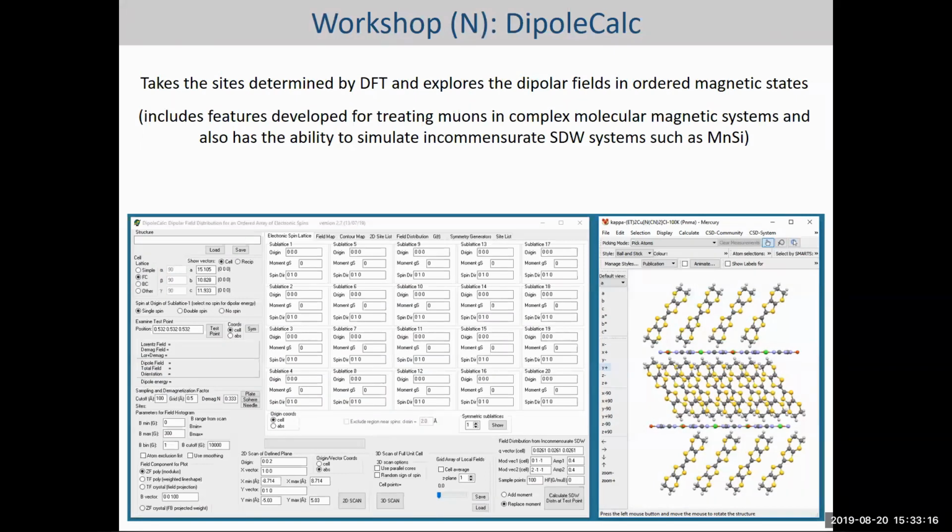Yeah, you showed in your tantalum calculations the muon sites, but you also showed some volume fraction of stopping, of number of muons stopping there. How did you get to those? Oh, well, that's just statistical. So the sites are just chosen randomly, and then they converge into a basin of attraction for each site. So you just count the fraction of the number of calculations that you've done there.